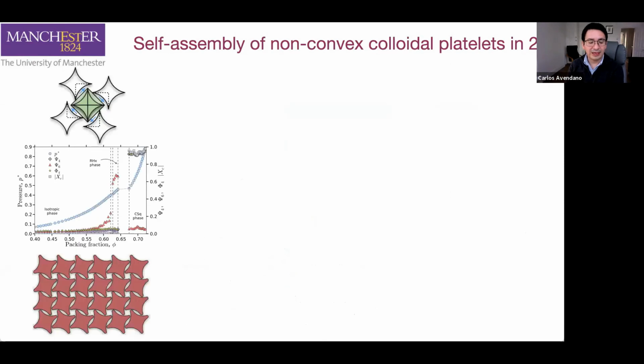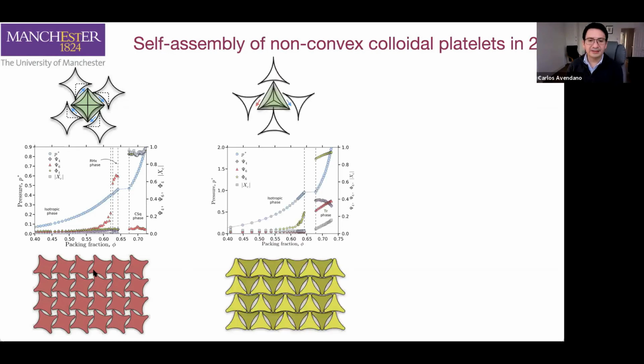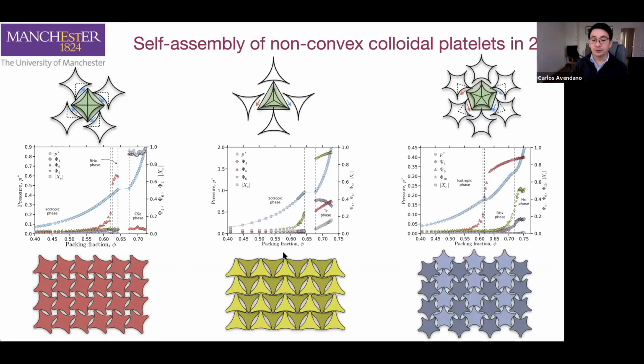We were able to analyze as well what happens with the square particles, and we observe exactly the same behavior. And we came up with a rule that as soon as the number of nearest neighbors around one particle is equal to the symmetry of the system, it will be able to form this kind of chiral structures. But when you don't have that symmetry, well, the system is going to try to pack in the best way that it can, but the formation of chiral phases hasn't been observed.